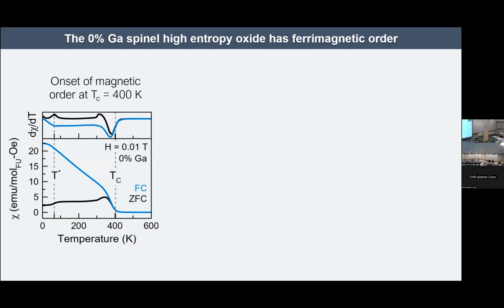And so once we had done that, we could see this beautiful onset of long-range magnetic order, which is marked by bifurcation in the field-cooled and zero-field-cooled susceptibilities. And so right away, we were thinking, oh, we have something like ferro or ferrimagnetic order.